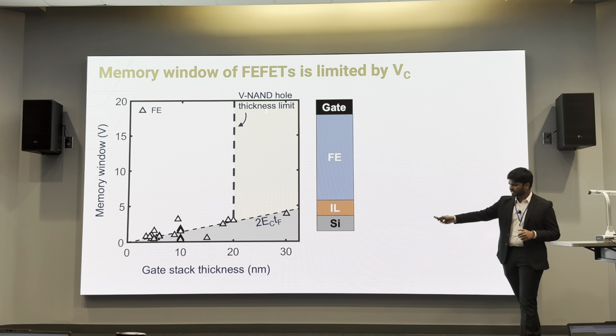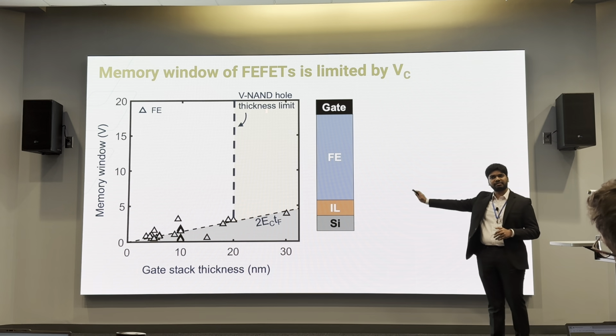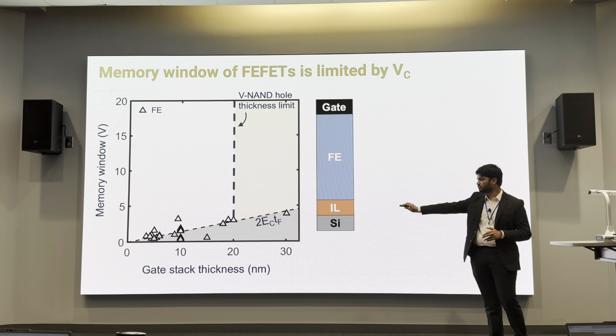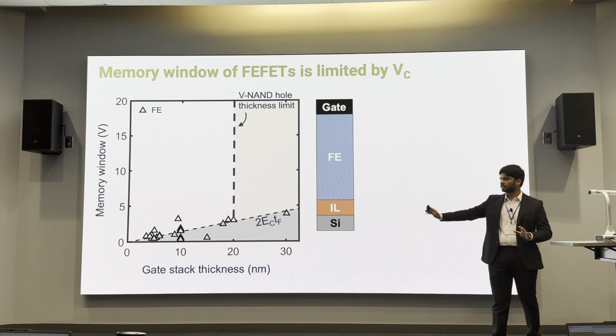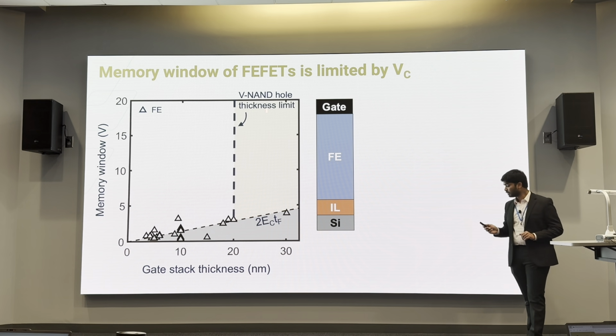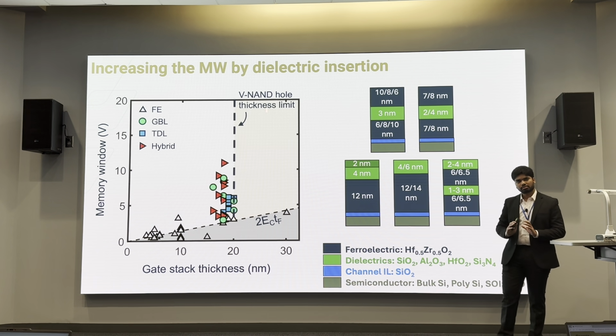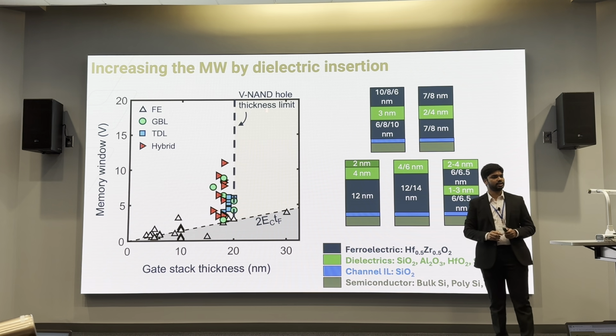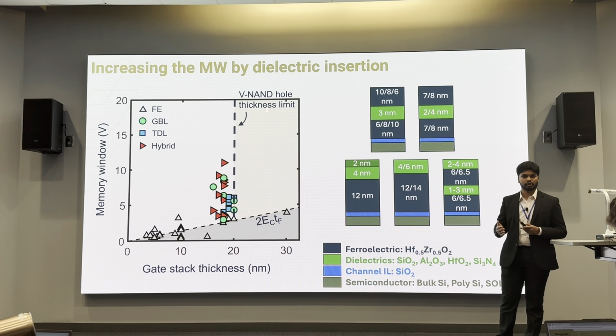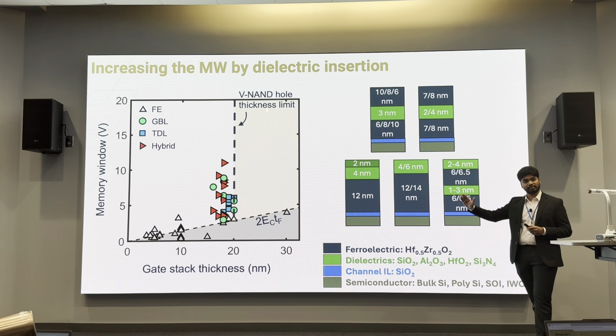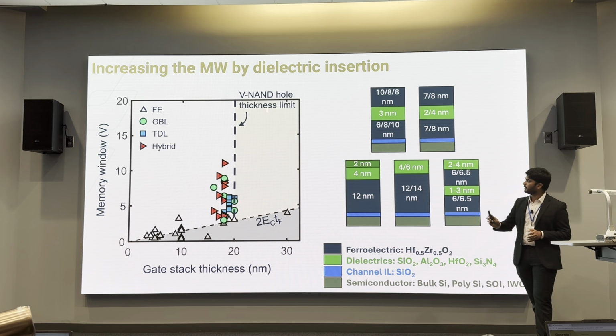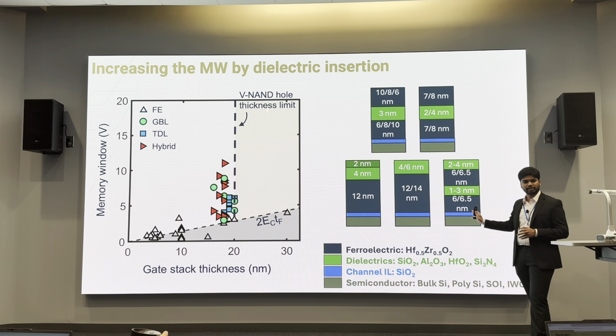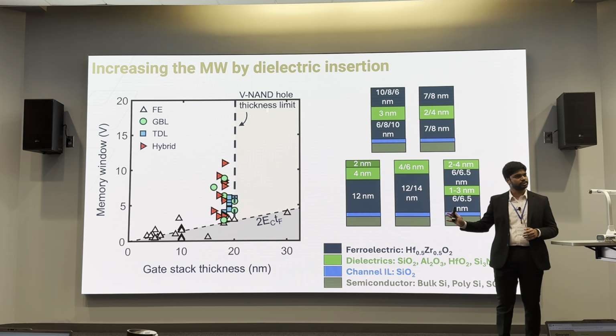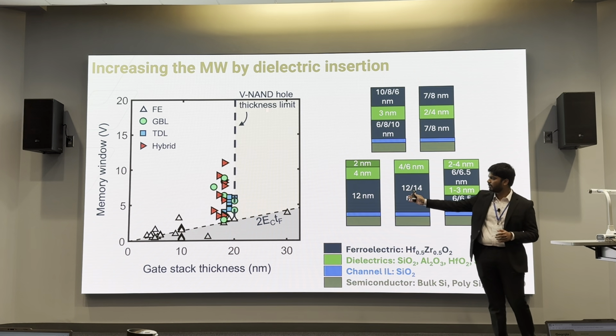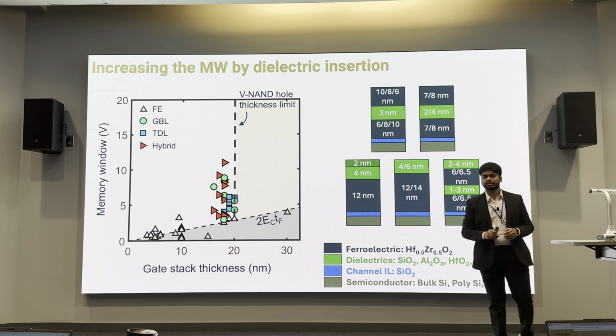So as we see here, most of the standard FeFET results are on the 2 Ec TF line, and at 20 nanometers it's just 3 volts. Over the last 2 years, we have realized that inserting a dielectric, aluminum oxide or silicon oxide, can improve this memory window significantly. And here are a bunch of different variants of dielectric inserts that we have tried out in-house at Georgia Tech, and we achieved a maximum of close to 11 volts.